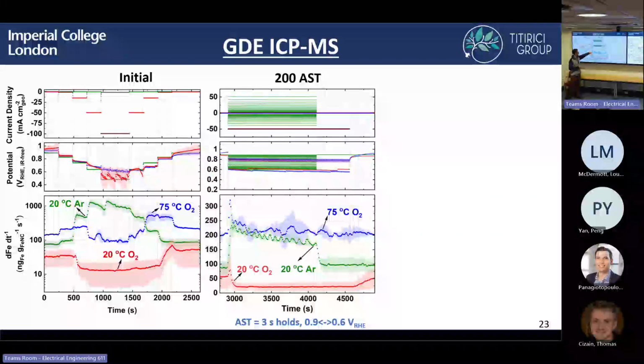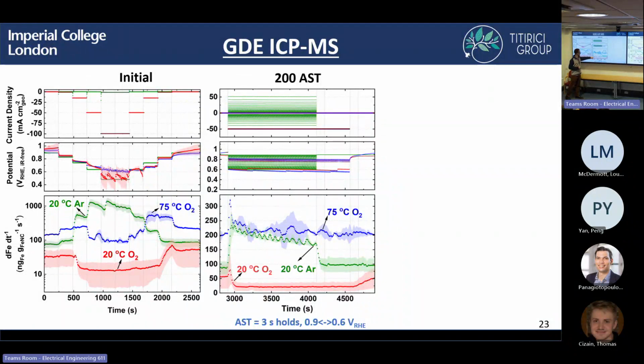In argon, we see this fairly consistent iron concentration increase over the measurement. In oxygen at 20 degrees, we see an iron concentration decrease over the whole period, whereas at 75 degrees, it seems to be relatively constant and a higher amount of iron concentration over the whole measurement. So again, very different.